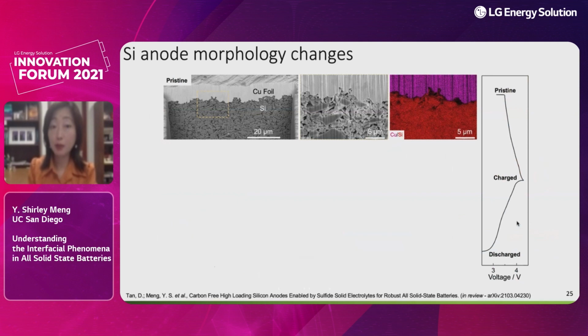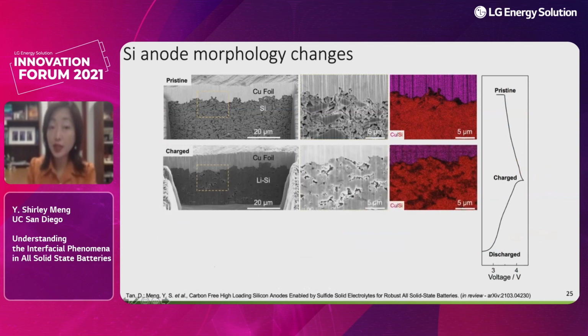If we take the pristine micron silicon particles, there's a lot of built-in particle morphology - you can see the large micron size silicon. Once we start lithiation, we found that yes, the dimension of the silicon does increase, but most of the dimension change goes into filling the pores.